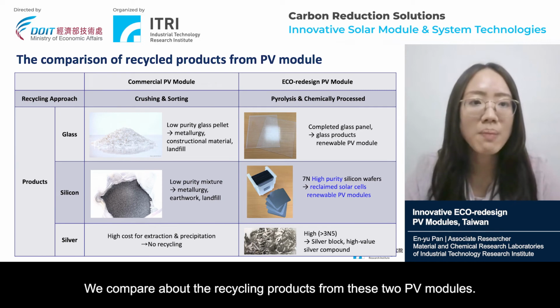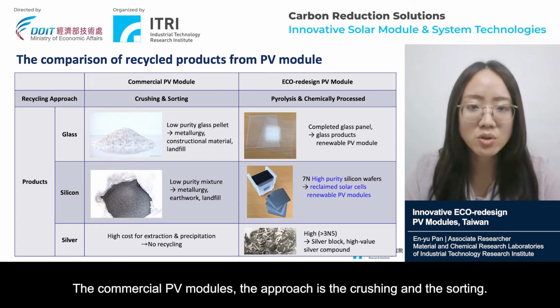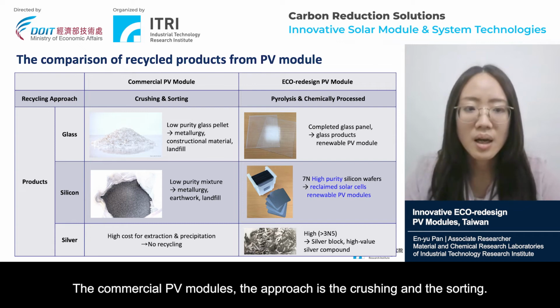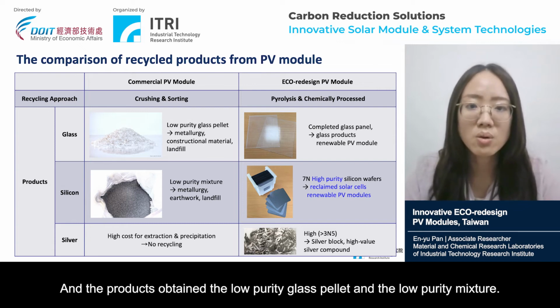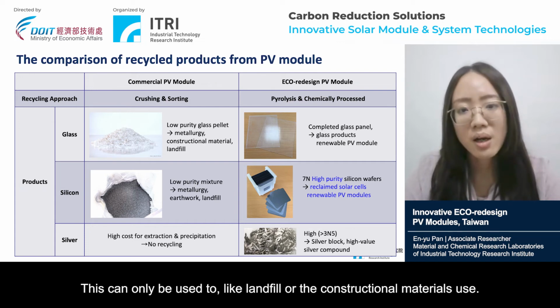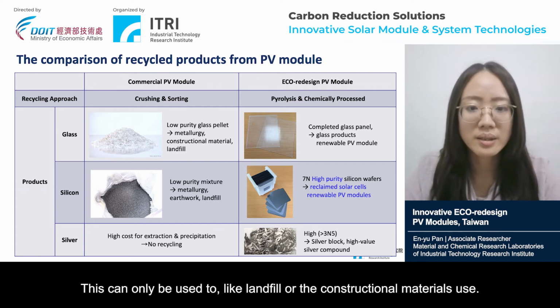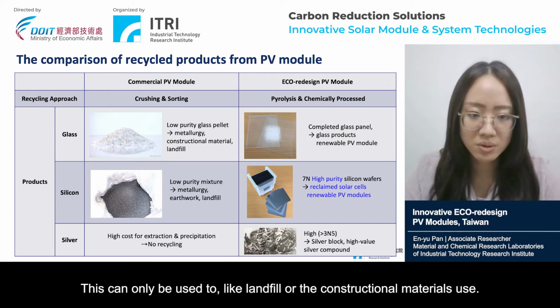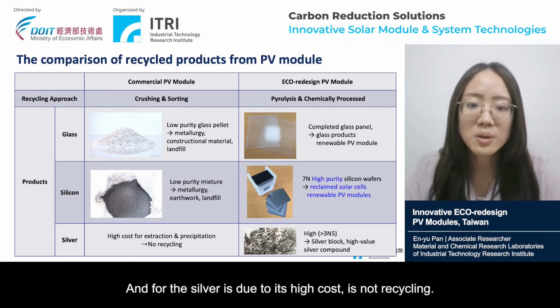And we compare the recycling products from these two PV modules. For the commercial PV modules, the approach is crushing and sorting. And the products obtained are low purity glass pellets and a low purity mixture. This can only be used for landfill or construction materials. And for the silver, because of the high cost, it's not recycled.